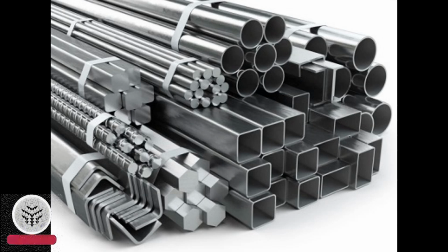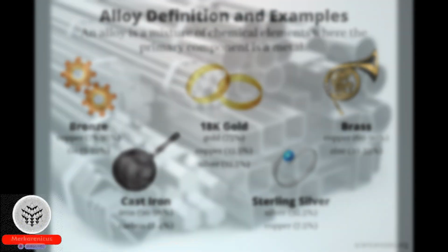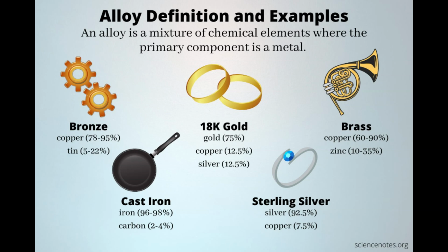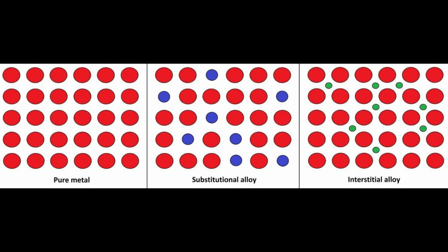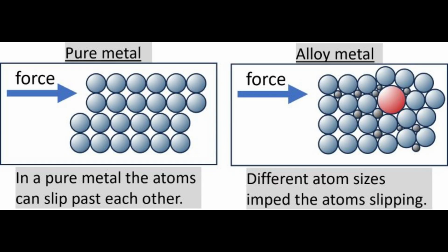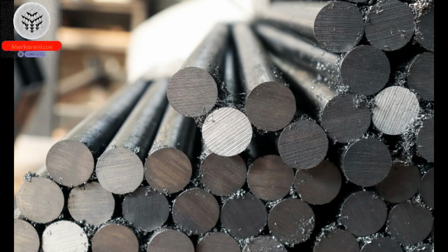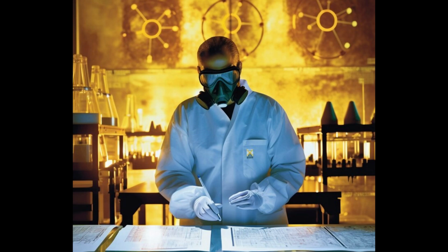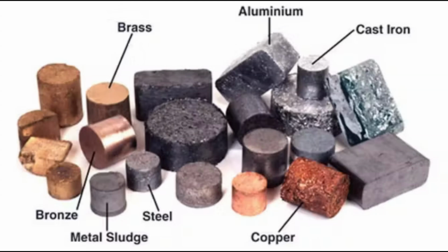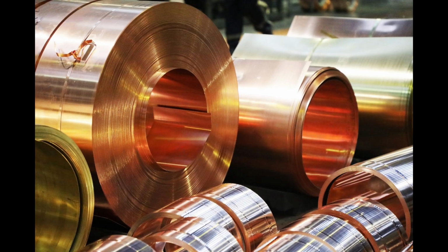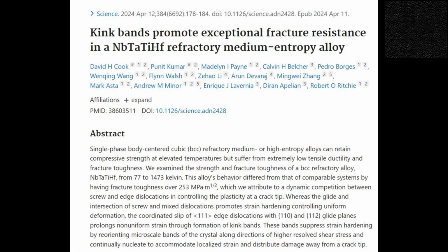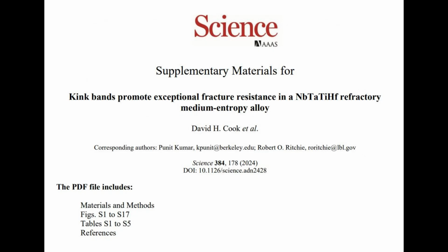According to Punit Kumar, a postdoctoral researcher in the group and co-corresponding author, their team has conducted previous research on RHEAs and RMEAs, revealing their exceptional strength but notably low fracture toughness. However, they were astounded when this particular alloy exhibited remarkably high toughness. As per Cook, the majority of RMEAs exhibit a fracture toughness below 10 MPa√m, establishing them as some of the most fragile metals known. Cryogenic steels, designed to resist fracture, are approximately 20 times more resilient than these materials.